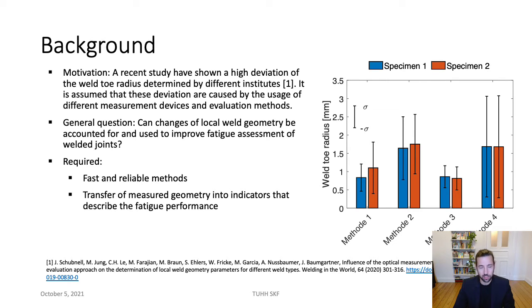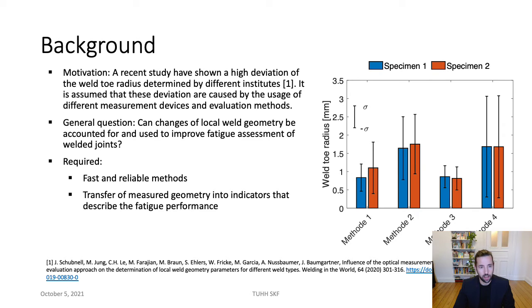When it comes to fatigue assessment and finite element modeling of welded joints, typically the geometry of welded joints is required as an input to build FE models. In a recent study together with some colleagues, we found out that methods used to quantify the geometry of welded joints can lead to quite different results for parameters of particular importance, such as the toe radius shown on the right. All four methods lead to different weld radii and show quite high variation in the obtained radii. This raises the general question of how changes in local weld geometry can be accounted for and used to improve fatigue assessment methods.